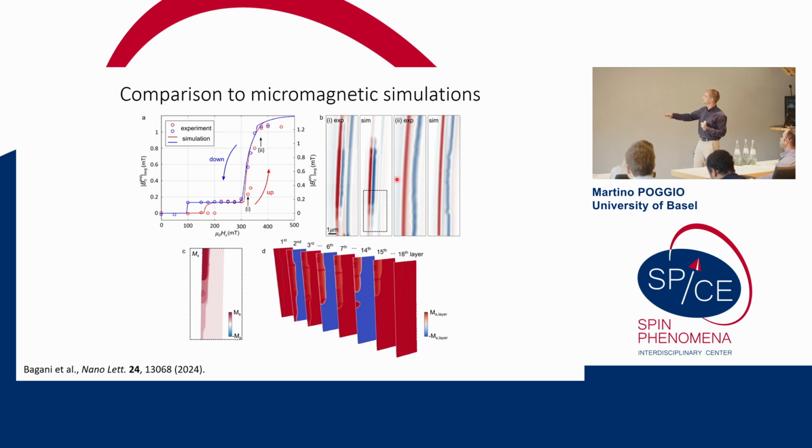So you can both simulate the kind of images that we measure here in space, and you can also simulate the kind of polarization curves that you measure using this kind of micromagnetic model. So it seems here that the dependence on strain is really what explains essentially everything that we measure. Even things that look like they might be due to defects actually have to do with the specific distribution of the strain in the sample.